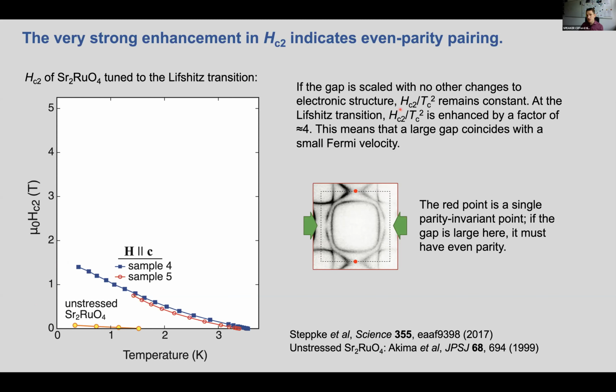The important quantity to look at is Hc2 over Tc squared. If you take a superconductor and you scale the gap without changing anything else in the electronic structure, then Hc2 over Tc squared remains constant. What we see as we go to the Lifshitz transition is that this quantity is enhanced by a factor of about 4. And what that means is that a large gap coincides with a small Fermi velocity more than in unstressed strontium ruthenate.